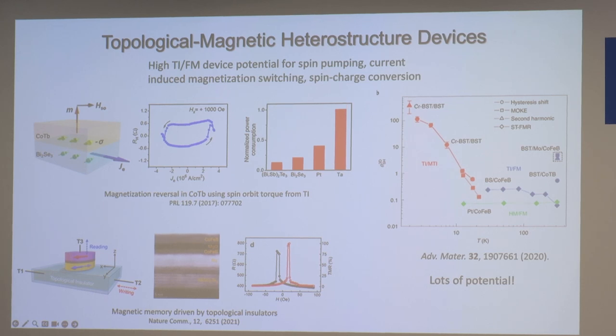And again, yesterday I talked about transistors and said that topological materials wouldn't be great for transistors because you can't carry a lot of current. They just aren't as effective as semiconductors in that case. But for spin devices, you actually want to do things with a low charge current and have a large spin current. So in this case, the current doesn't affect you. In fact, it's really good that you can get a large spin current out of a pretty low charge current. So these do have a lot of potential for actually practical devices. I will say that the challenges here are, it's a challenge to switch the magnetization of the surface state.